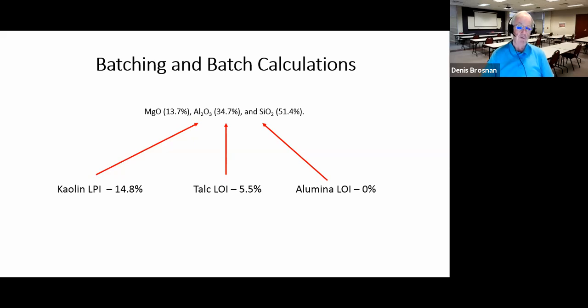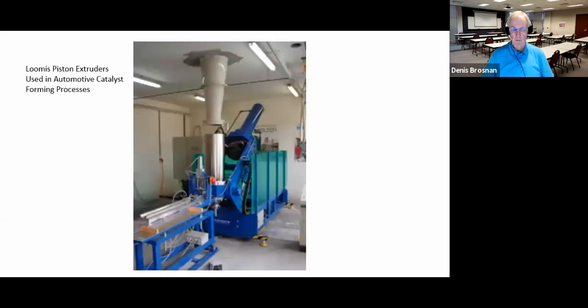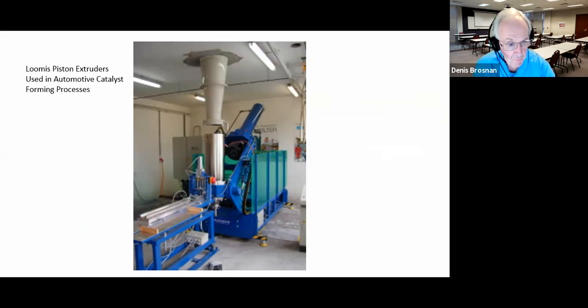That's good. So after we batch it, we have to mix it up and we have to do a good job of mixing. I can't spend more time on batch calculations. That's something others should have done in this ceramic sequence. So typically we're going to use a piston type extruder to make this product. At least that's the way it was in the beginning. So we drop a batch in a cylinder. That cylinder rotates down. There's a piston that's going to push that material forward. All this, once it's folded down, is horizontal, and it pushes out the cordierite onto a tray here. Tray is necessary because the green strength is not good when this product is made.